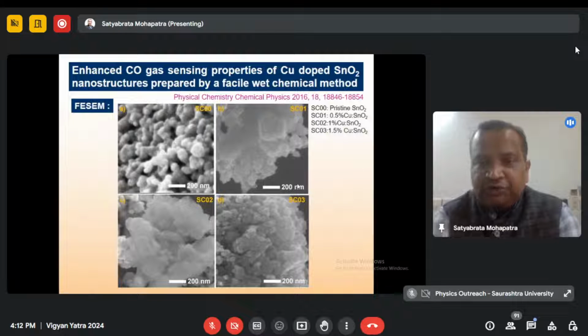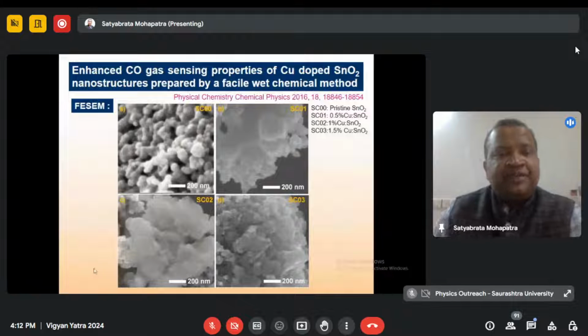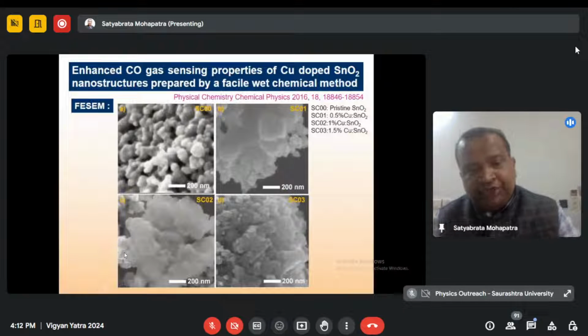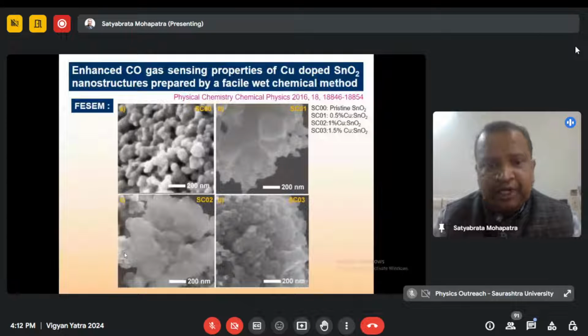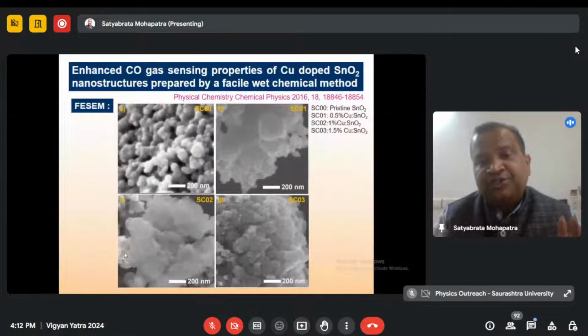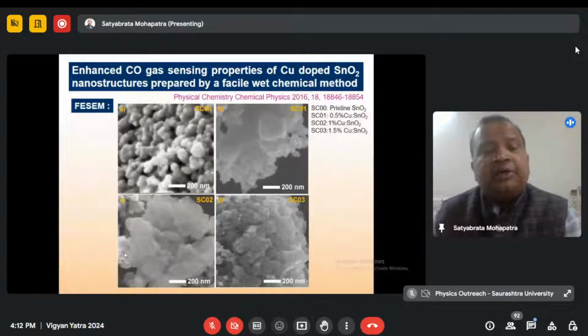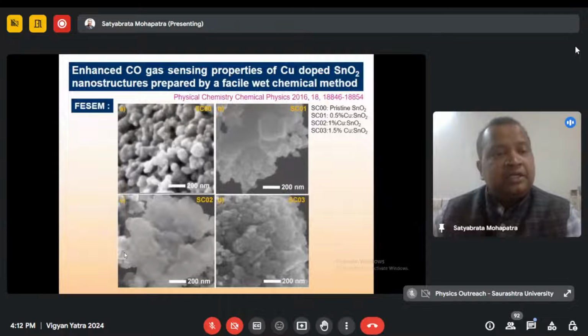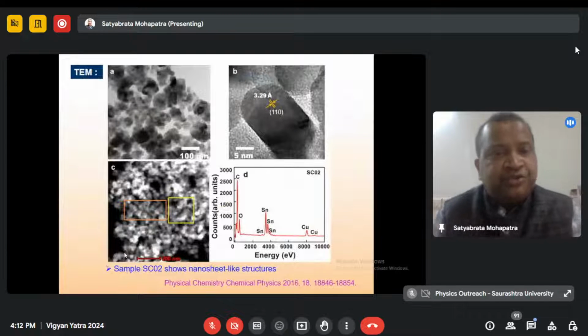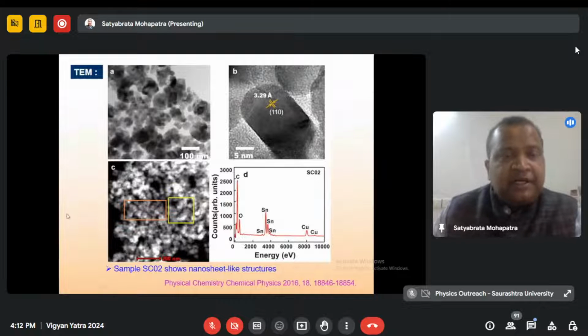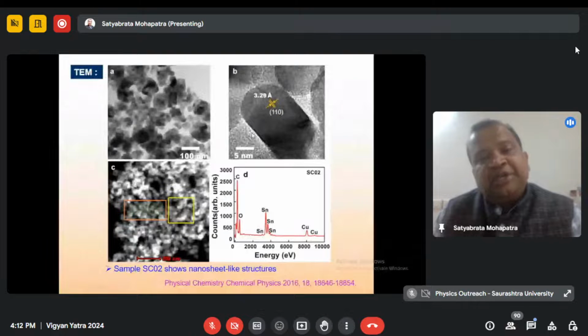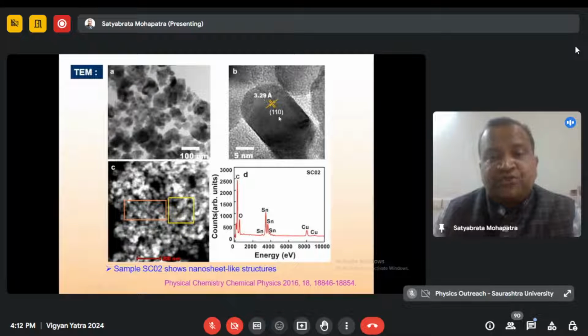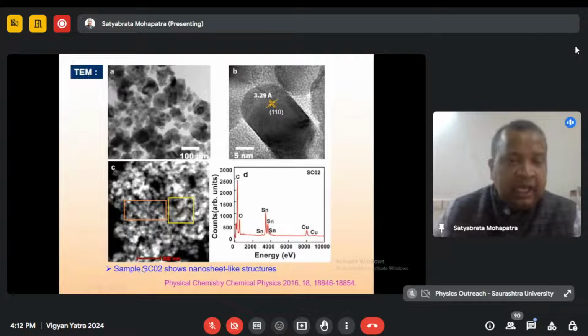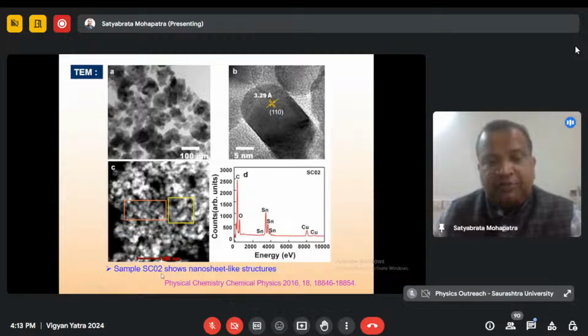And you can see the respective FESEM images, in which SC01 and SC02 show distinct flake-like structures, and as you can see, they consist of nanosheets, which is clear in the TEM image. The TEM image clearly displays nanosheet-like structures, and the HRTEM confirms that this is tin oxide. This is 3.29 angstrom, 110 lattice planes clearly visible, and of course the EDAX spectra again confirm that these are copper doped tin oxide nanosheets.